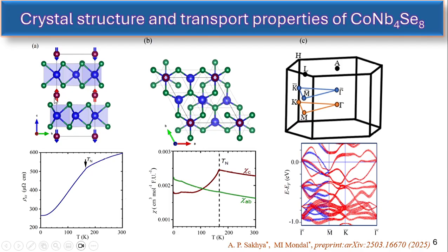These cobalt atoms are located at the one-quarter octahedral location that makes the crystal centrosymmetric. The cobalt atoms are ferromagnetically aligned in plane, but they are stacked antiferromagnetically along the out of plane direction. This is one of the required properties for exhibiting altermagnetic behavior in a material.